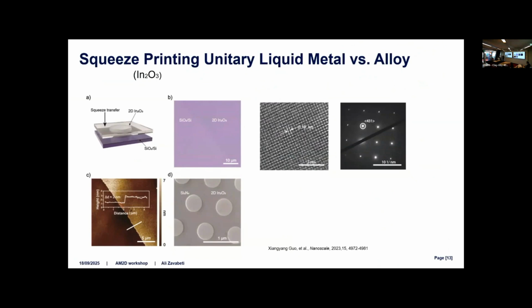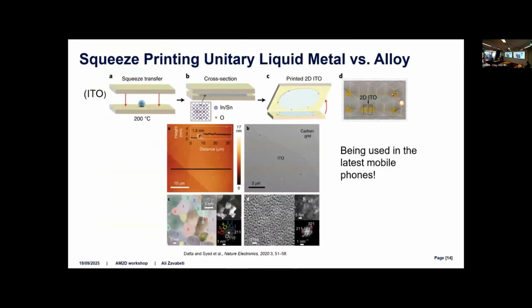Basically, indium melts at just above 150 degrees. So we place a hot plate at around 200, just above 150, and we can 2D print these very nice indium oxide layers. ITO is widely used as a contact material. It's a TCO, transparent conductive oxide. We have shown that if you mix indium and tin and squeeze print, we can get ITO as thin as just a few nanometers. So here is 1.5 nanometers. We can multiple print or just single print, and we show it is conductive.